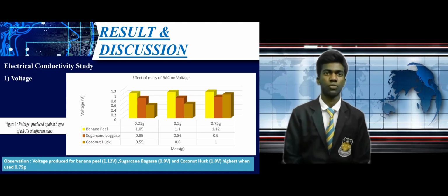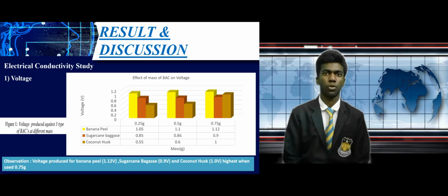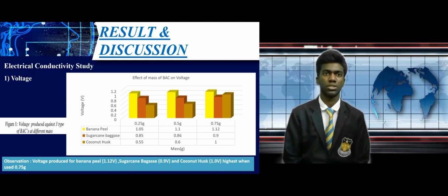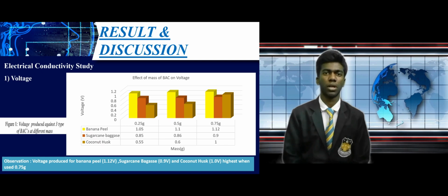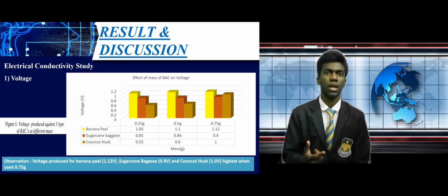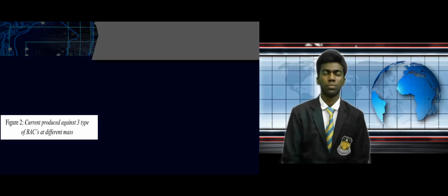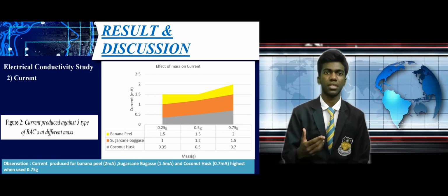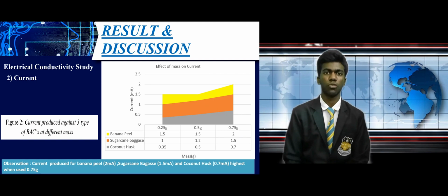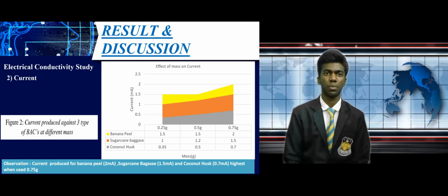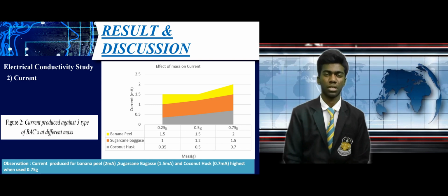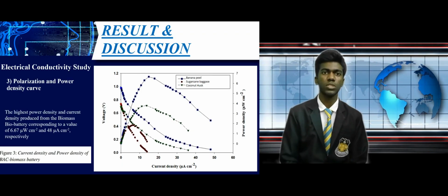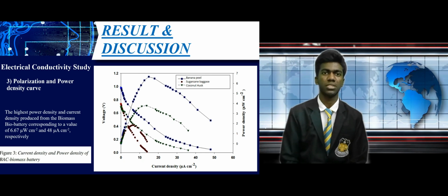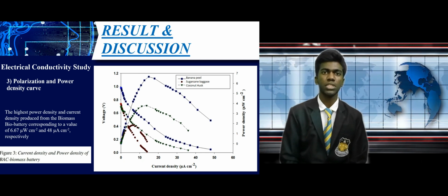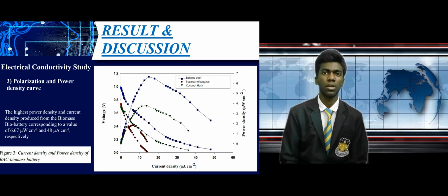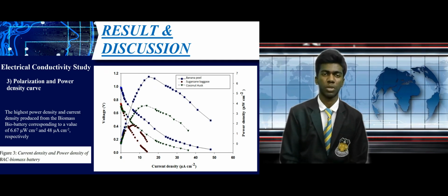In the voltage against mass graph, we can see that when 0.75 gram of BAC powder is used, the voltage produced is the highest, which are 1.12 volt for banana peel, 0.9 volt for sugarcane bagasse and 1.0 volt for coconut husk. Based on the current against mass graph, we can see that the current produced is the highest, which is 2 mA for banana peel, 1.5 mA for sugarcane bagasse and 0.7 mA for coconut husk. In the last test, we found that the highest power density and current density produced from the BAC biobattery correspond to a value of 6.67 microwatt per centimeter square and 48 microampere per centimeter square respectively.